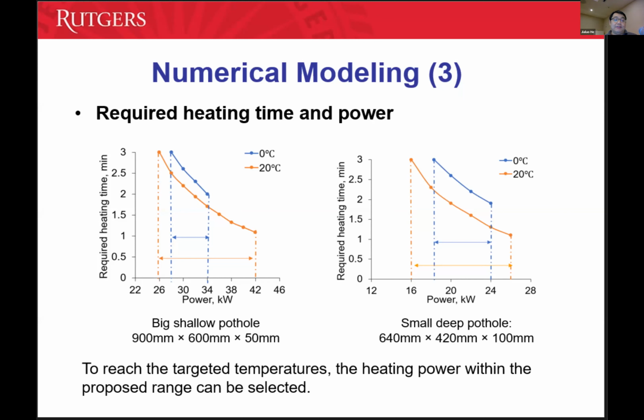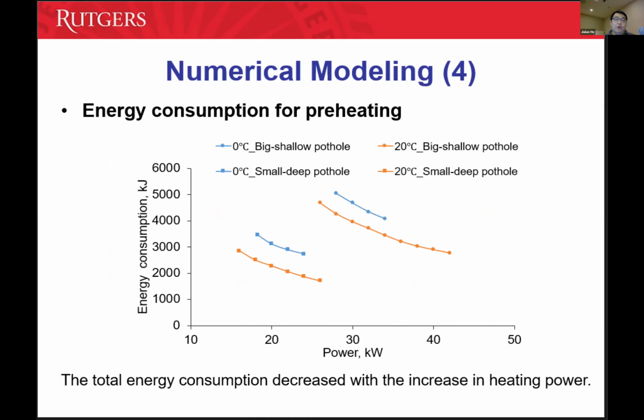So we did this sensitivity analysis, and we limited the heating time to 3 minutes, which is easier for practical implementation, and looked at the required power, which is actually achievable with the current infrared heater machine. We're also looking at energy consumption, because one criticism may be that we are applying more energy. From a life cycle point of view it is beneficial, because although you can increase the longevity, you add more energy during the production stage.